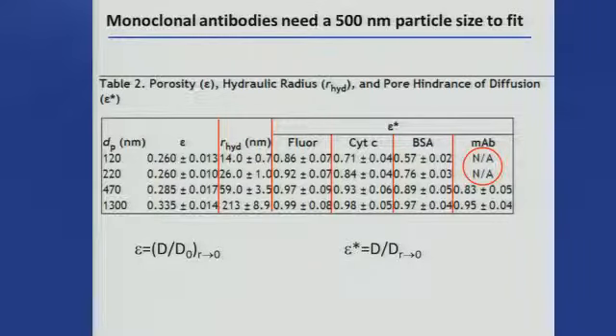And so we measure that with this equation, and then we look at how much of this porosity is available to the protein. If it's fluorescein and it's a big particle size, almost all of the free volume is available to fluorescein, and it is all the way until you start really getting down onto the molecular scale. So the particle looks big, but the spaces between the particles are really tiny. So even fluorescein can't reach all of the free volume.